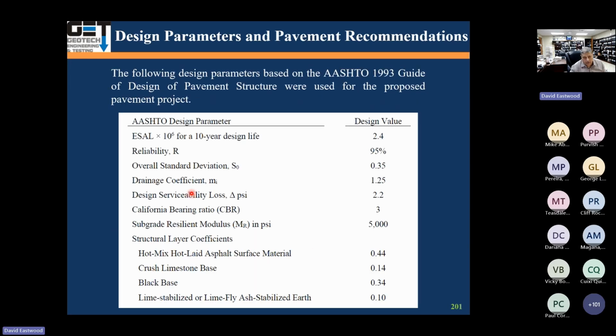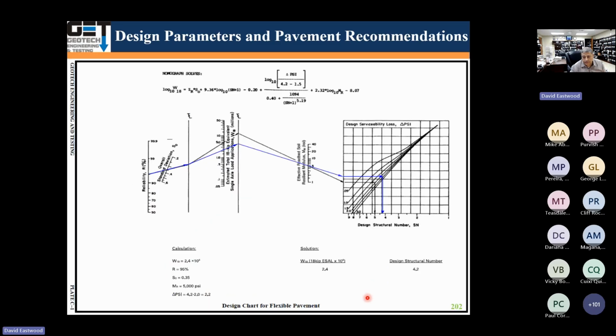Here are some of the design parameters we used. Traffic loading, 2.4 million. Reliability, 95%. Overall standard deviation, 0.35. Drainage coefficient, 1.25. Design serviceability loss, 2.2. CBR, 3. Resilient modulus, 5,000. Structural coefficients are here: asphalt, 0.44; crushed limestone, 0.14; black base, 0.34; and lime stabilized, about 0.11.